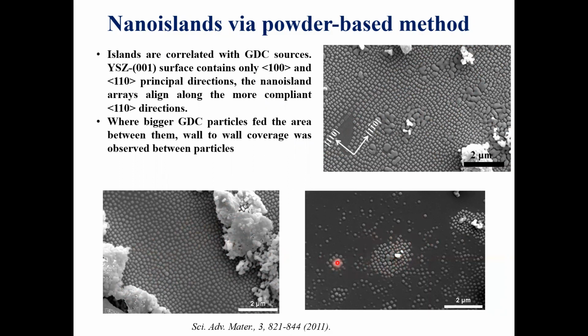And if you do the chemistry and crystallography on this nano-island, it has exactly the same chemistry and crystallography, and they align along the 110 direction, the softest elastic modulus direction of the substrate. So this is very interesting.